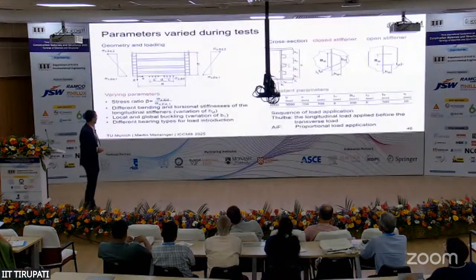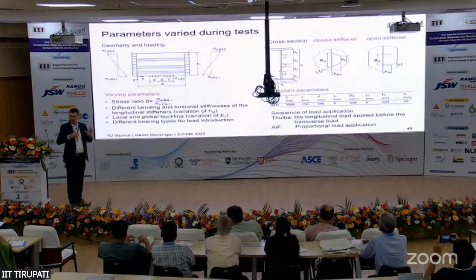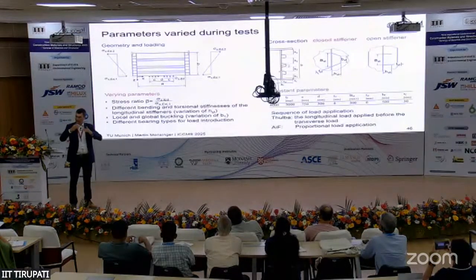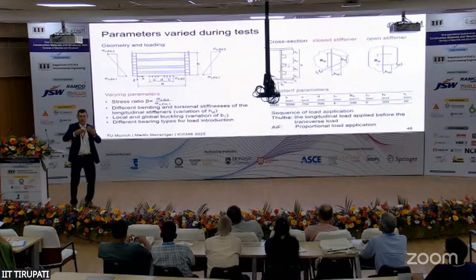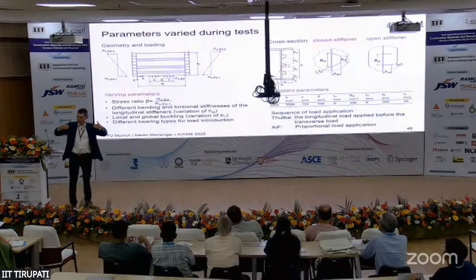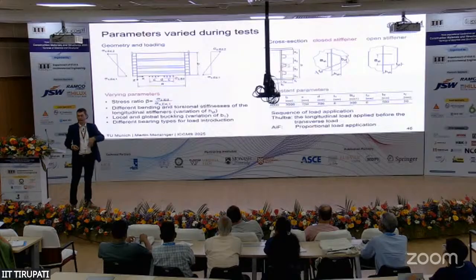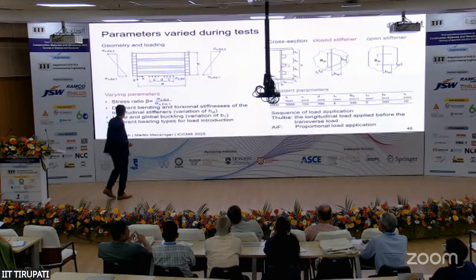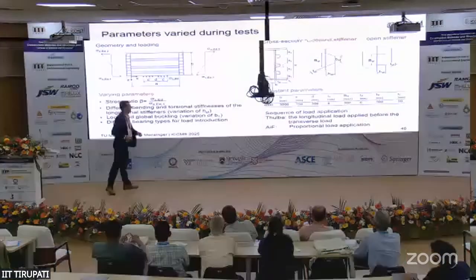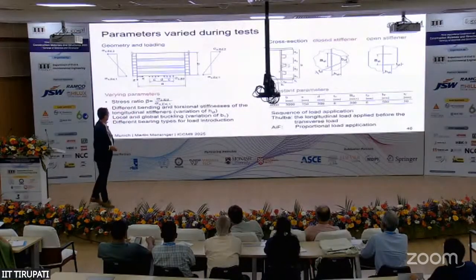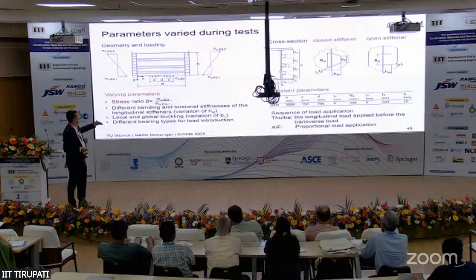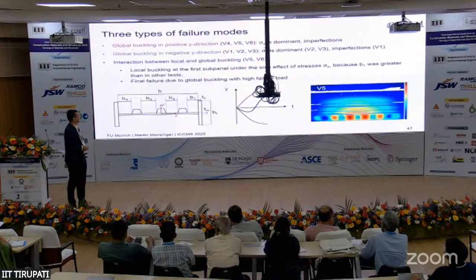Okay, we varied, and therefore it is important how the relation of the stresses in X direction compared to the stresses in Z direction is, because the stresses in X direction might lead to this multi-wave buckling, which then enhances the bearing capacity for cross-directional load. And therefore, that was one reason we varied this in our tests. We kept some parameters constant, but overall we had a lot of variations.